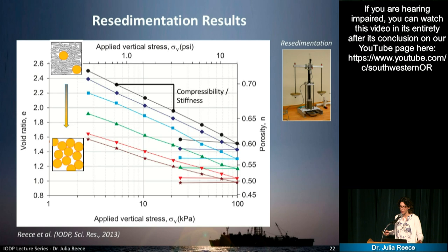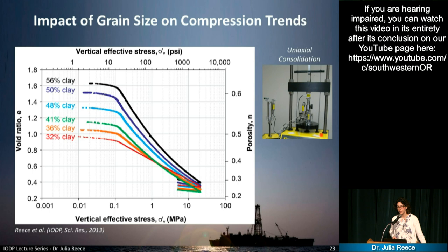And now we can take this to another level. We have this little resedimented sample, which was only stressed to very small stresses, but if we are interested at high stresses, then we can take the sample and put it in this load frame, which can then take it to stresses that go to 20, 30 megapascal, which is about 2 kilometers, 3 kilometers of burial.